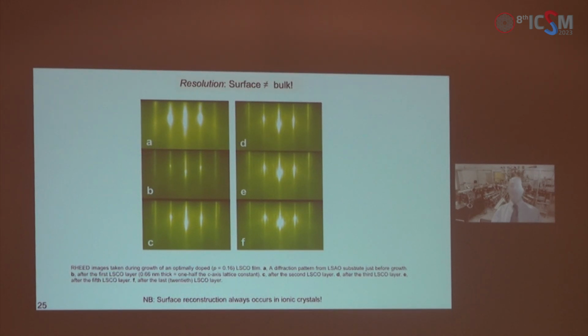And what I always see is this: some extra sidebands in between the main streaks, which are the 0th, 1st, and 2nd order Bragg reflections. These sidebands show that there is a surface reconstruction. The unit cell at the surface is enlarged, typically a 4 by 1 or 5 by 1 reconstruction. And that's after cuprate deposition. But note that this superstructure was never observed in the bulk.